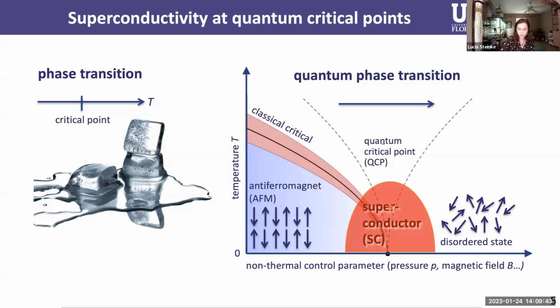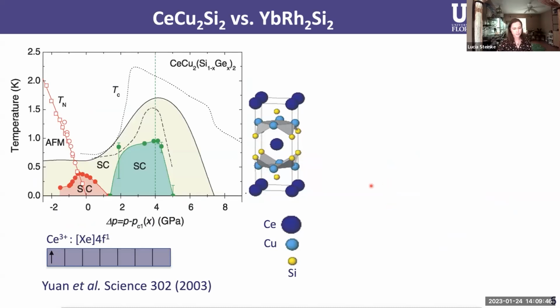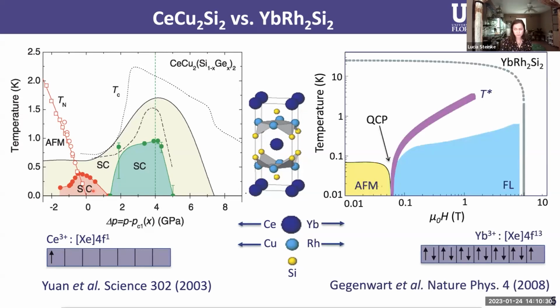Now, does this hold true for the first unconventional superconductor? Yes, it does. So here's a phase diagram that was measured for cerium copper two silicon two. Now, the non-thermal control parameter is a combination of hydrostatic pressure and chemical pressure. So that was achieved by germanium substitution. And I don't want you to get lost in the details of this phase diagram. There's quite a few superconducting phases here, but I want you to pay attention to this one. So there's the superconducting dome that occurs right where an antiferromagnetic phase is suppressed to 0. So superconductivity at quantum critical points appears to be true in the first unconventional superconductor discovered by Frank Steglich. But it was also the Steglich group who found that in the same class of materials, there was an apparent outlier, some oddity. And that was ytterbium rhodium two silicon two.